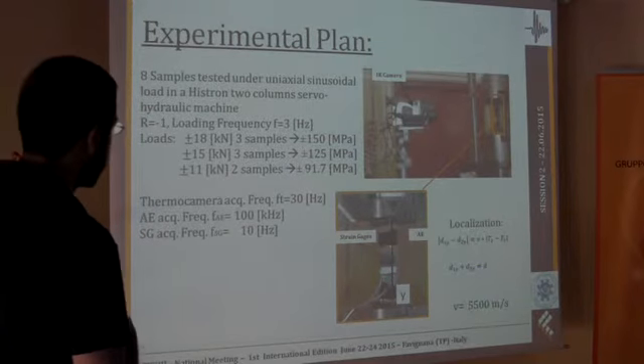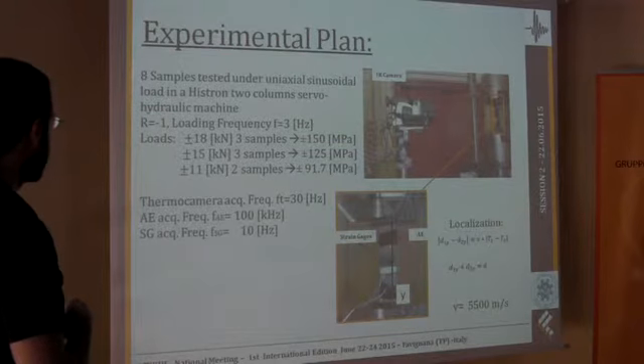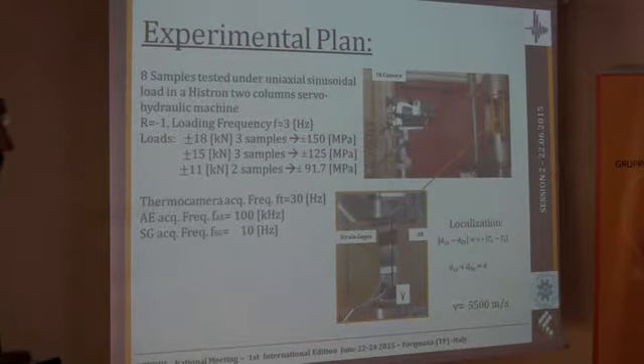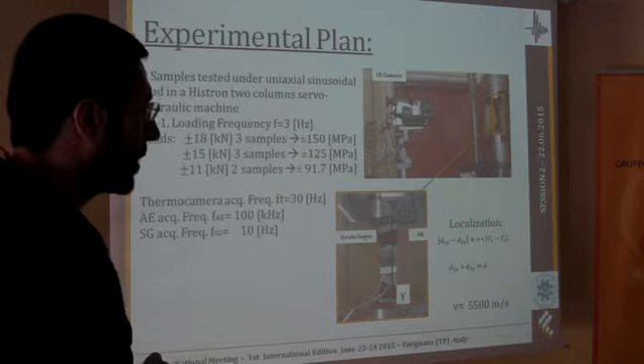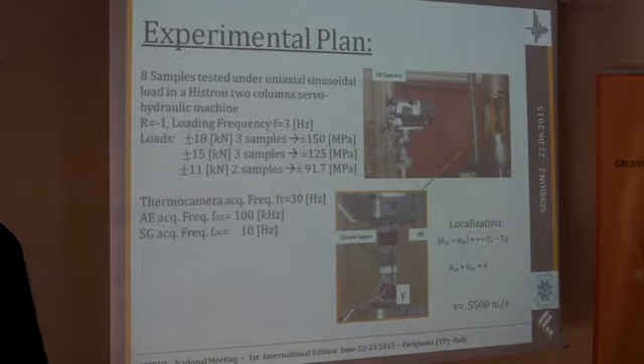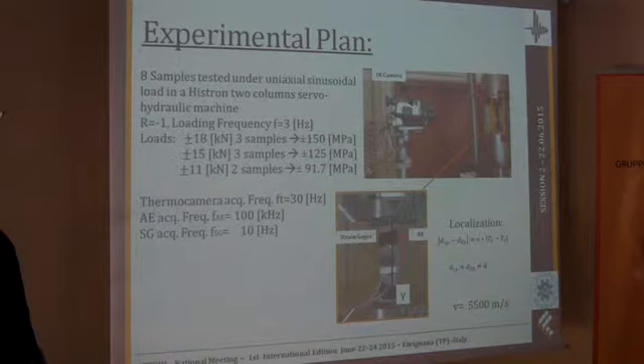The thermal camera acquisition frequency was set at thirty hertz, the acquisition frequency for acoustic emission system was set to one hundred kilohertz, and the acquisition frequency for the strain gauges was set to ten hertz.